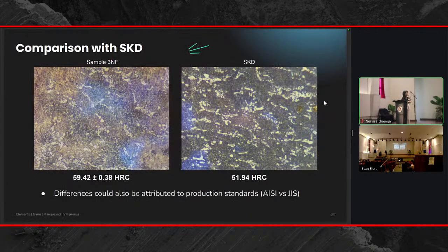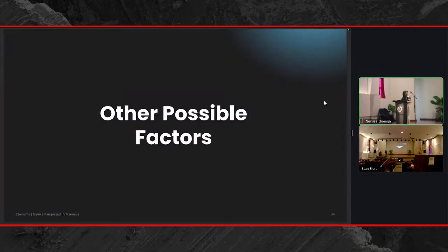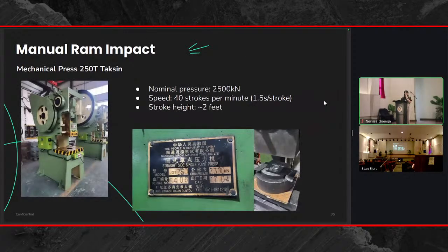So, all right, I will be glossing over this. However, because there are other possible factors that we unfortunately had limited time to check, but still wanted to consider. The first is the actual manual ram impact force. So these samples failed under operation of a mechanical press instead of hydraulic press. So the mechanical press, essentially what happens here is that the die is loaded up into the mechanical press and then released abruptly. So ito ang nominal pressure and speed that we obtained from interviews with the client.